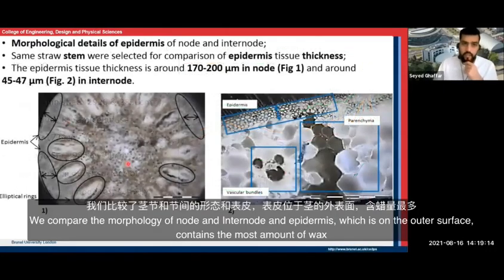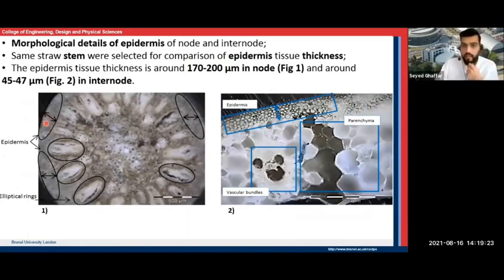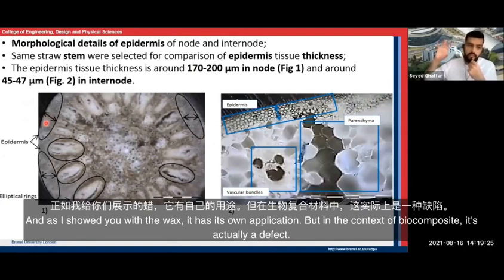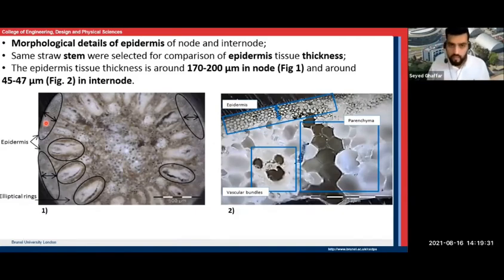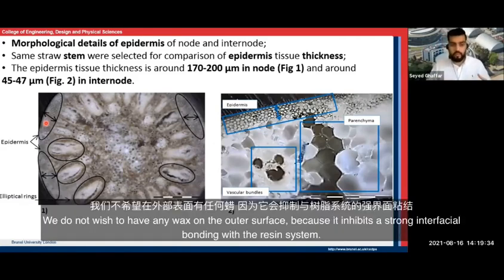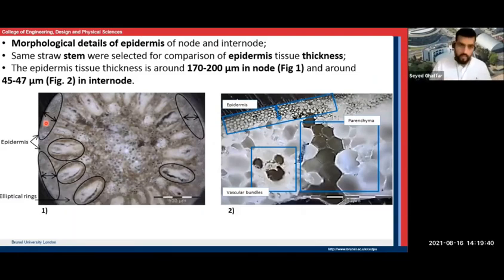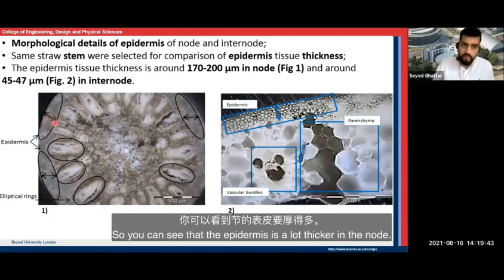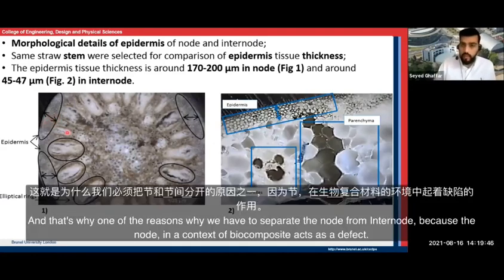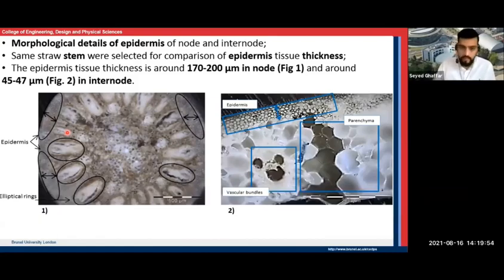We compared the morphology of node and internode, and the epidermis, which is on the outer surface, contains the most amount of wax. And as I showed you, the wax has its own application, but in the context of biocomposite it is actually a defect. We do not wish to have any wax on the outer surface because it inhibits a strong interfacial bonding with the resin system. So you can see that the epidermis is a lot thicker in the node, and that's one of the reasons why we have to separate the node from internode, because the node in the context of biocomposite acts as a defect.